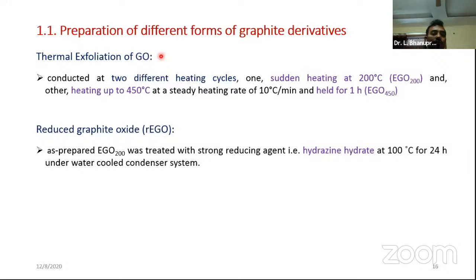And then from the graphite oxide, we have thermally exfoliated it in two ways: by suddenly heating it at 200 degrees centigrade, and by gradually heating up to 450 degrees centigrade. In two ways we have exfoliated it, and then finally we have chemically reduced it to bring it into graphene shape, graphene nanoparticles. We reduced it using a strong reducing agent, that is hydrazine hydrate.